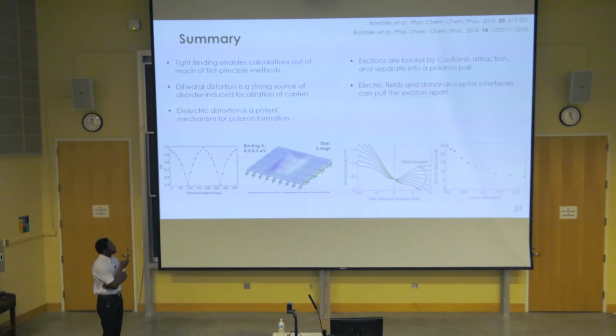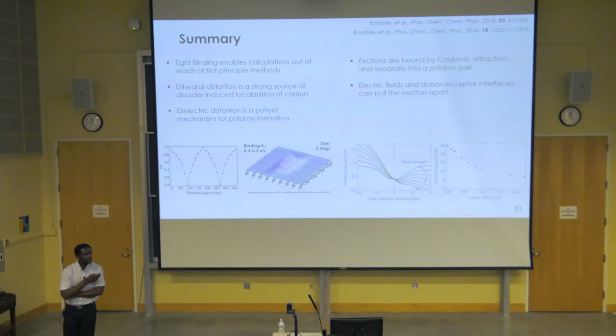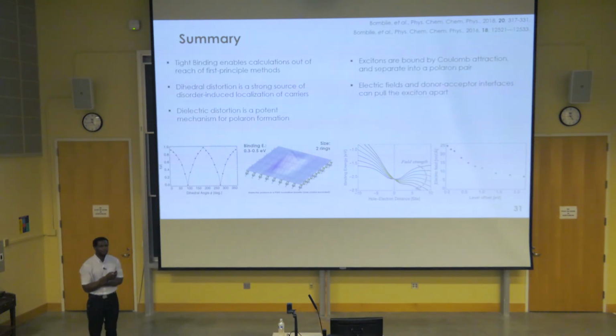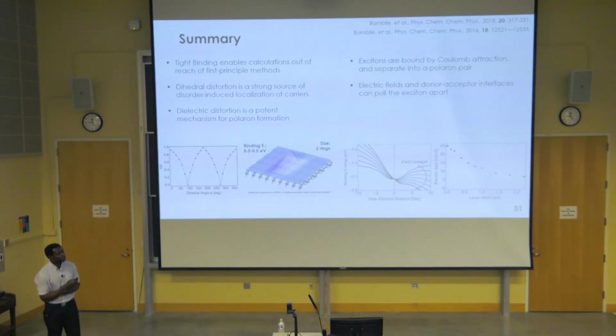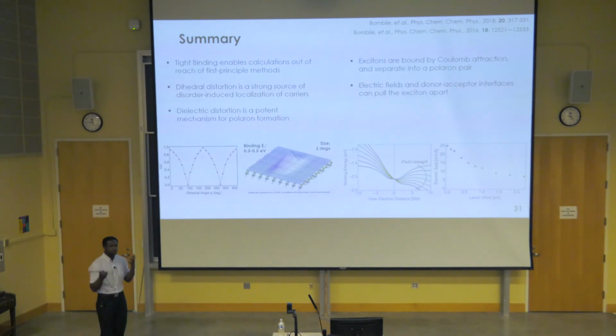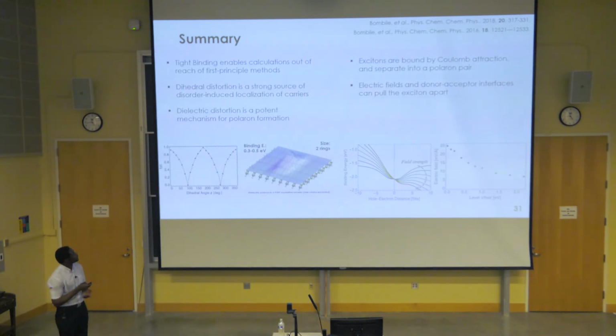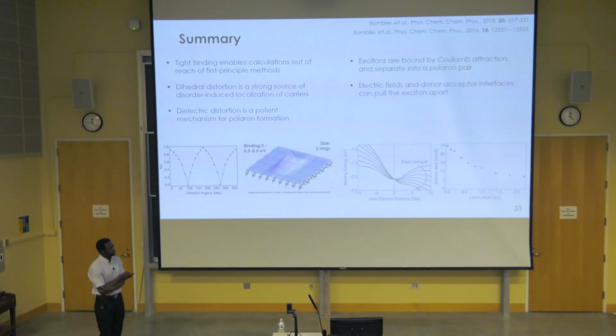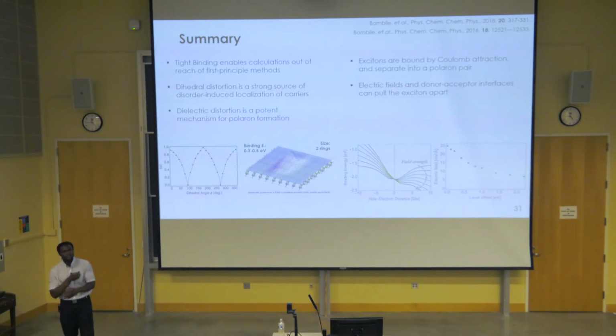So with that, I will summarize my talk. I've shown you a simplified model based on the tight-binding approximation that we use to investigate the electronic properties of semiconducting polymers, with a link to the structural changes within the material, something that is difficult to perform using first principles methods such as density functional theory. I've also shown you that the distortion of dihedrals within the material is a strong source of localization of charge carriers through the mechanism of disorder. And I've shown you that dielectric effects are a potent mechanism for polaron formation in these materials.